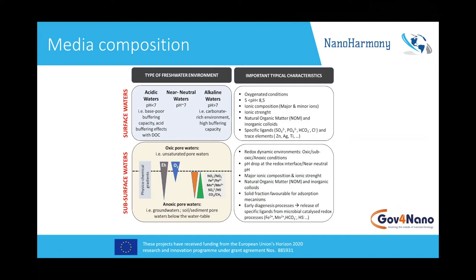As controlling factors, pH is one of the major factors, and DOC — natural organic matter — is also a major factor. We have chosen a range of acidic to alkaline waters with three different settings: pH from below seven to above seven, specifically from 5 to 8.5. We will use background electrolytes to control ionic strength and then use trace components found in surface waters that can drive reactions towards transformation.